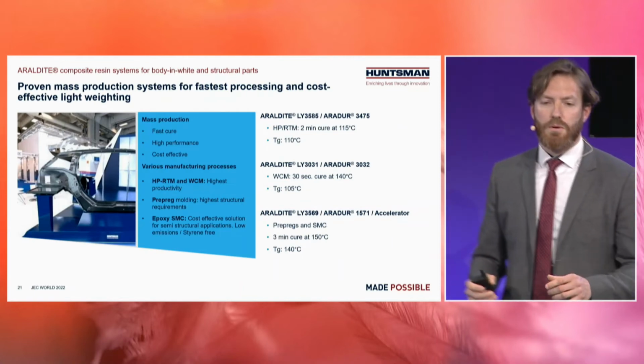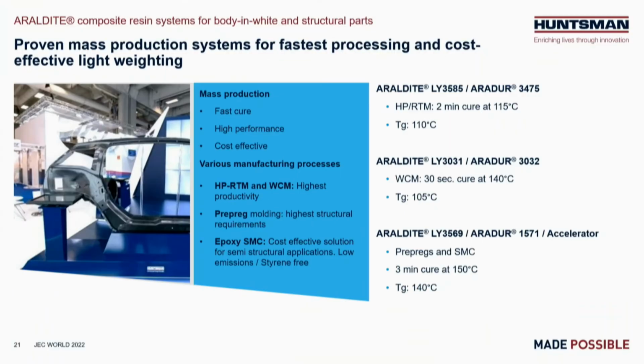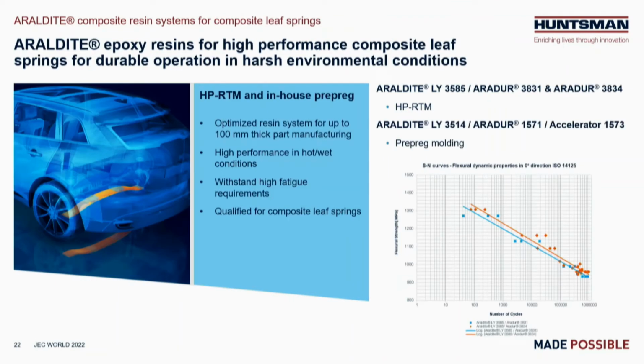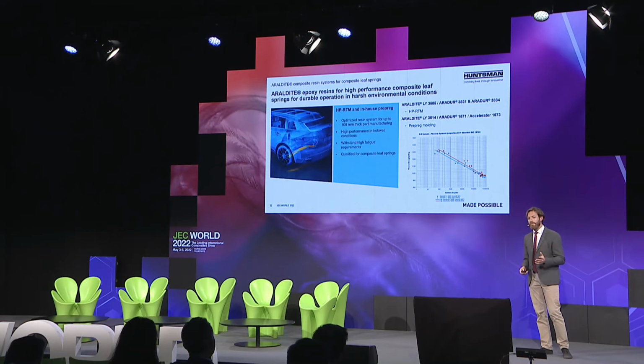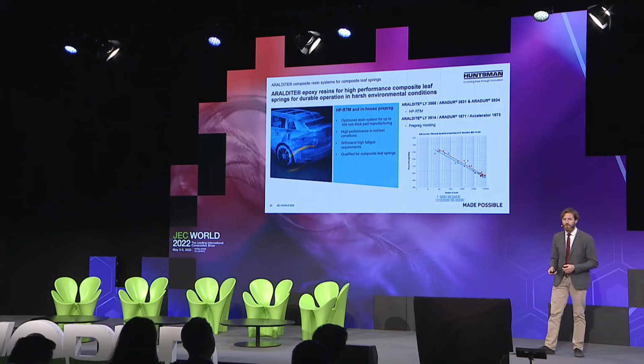Then a few words about the proven mass production process. This is not really new in our portfolio, but at least it's running in production. We have several resin systems for high pressure RTM and wet compression molding with very fast cure times, which are also highly structural. And the same for leaf springs, where we have been focusing on fatigue resistance, so we're generating a lot of data on the parts, on the coupon level. For example, here are some SN curves that we've done on those 2 examples of resin system, also compatible with high pressure RTM or prepreg, depending on the requirements of the customers.